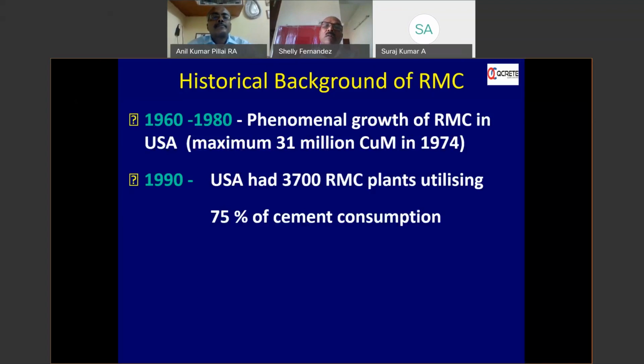Now, a background about RMC. From 1960 to 1980, there was a phenomenal growth of RMC. In the USA, around 31 million cubic meters was being done through ready-mix. Around 1990, the USA had around 3,700 plants utilizing 75% of the cement consumption. Right now, we can say around 6,000 RMC plants are operating in the USA, and in most developed countries 85 to 90% of the cement consumed is moved as ready-mix concrete, whereas India has not come up to that stage. We are only at a penetration level of 15%.